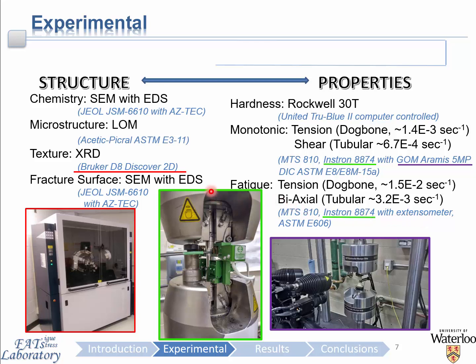The details by which the experimental investigations to characterize both the structure and properties were conducted are as follows. Biaxial fatigue tests were done over several frequencies ranging from 0.1 Hz to 30 Hz to maintain an approximately equivalent strain rate between all of the tests. Both the monotonic and fatigue tests were conducted using servohydraulic controlled load frames with digital image correlation used to measure the strain in the monotonic tests, and an extensometer used to measure the strain in the fatigue tests. The chemistry of the alloy was obtained via scanning electron microscopy with EDS, the microstructure with light optical microscopy, and the texture with X-ray diffraction shown here. The fracture surfaces of the monotonic and fatigue samples were investigated using SEM as well.